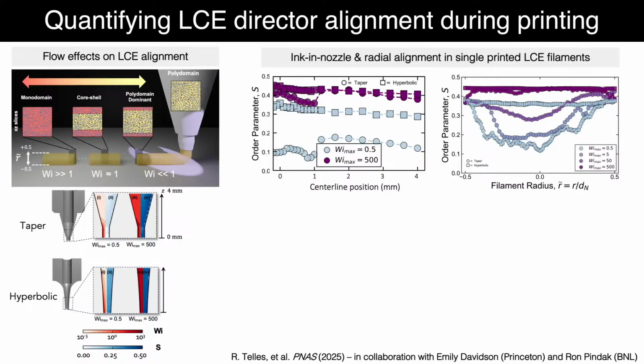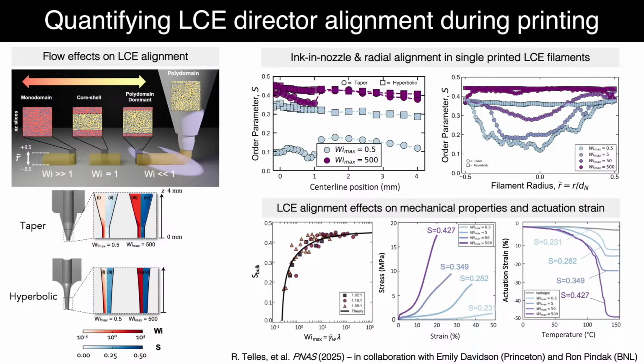And then we can look across the radius of this nozzle and also ask ourselves, what is the variation across the internal structure? And if you want to encode a high degree of orientational order, then we essentially want a tapered nozzle, because it looks quite uniform across both the center line as well as the radius, and we want to work at high Weissenberg numbers. And so with that, we can see that as we characterize the bulk orientation as a function of the maximum Weissenberg number, where here the shear rate at the wall is the highest shear rate across the nozzle radius, we're approaching a steady state value of about 0.45.